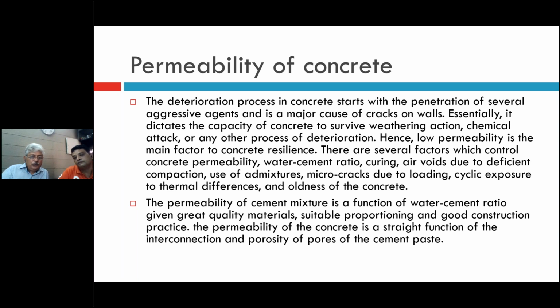micro cracks due to loading, cyclic exposure of thermal differences, and oldness of concrete. So these are the things we have to take care of while we are making any structure. The permeability of cement mixture is a function of water cement ratio, given grade, quality material suitable for proportioning, and good construction practice. The permeability of the concrete is a straight function of the interconnection and porosity of pores of the cement paste. So wherever bad workmanship comes, this defect will come.